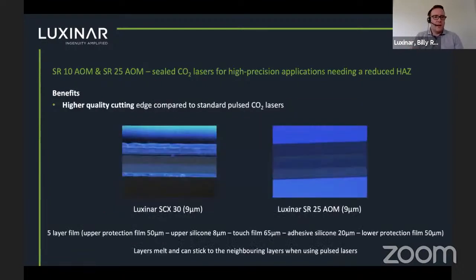Similarly, looking at a 5-layer film here. So this is a material where you would partially process the material, so only some of the layers of the film you would want to process. A problem that can occur with these materials is that the layers will melt and stick together to the neighboring layers. But using a Luxinar SR25 AOM laser here, you can see that you get a much cleaner cut quality compared to a standard CO2 laser.